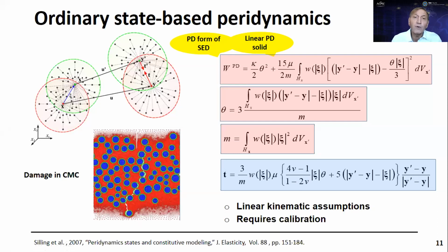It also requires calibration. And there is an example of what you can achieve in terms of crack growth pattern estimation. This is a cross-section of a ceramic matrix composite. You have a pre-existing crack here. It basically very nicely, in an autonomous way, gives you the propagation path for the crack.